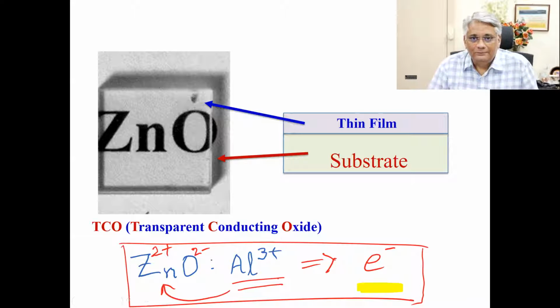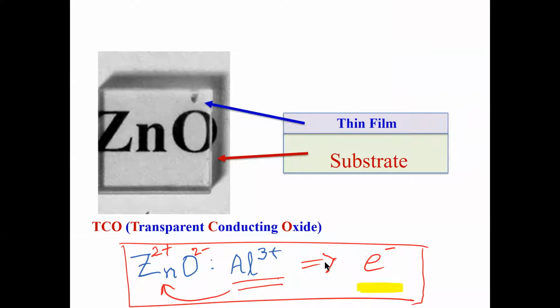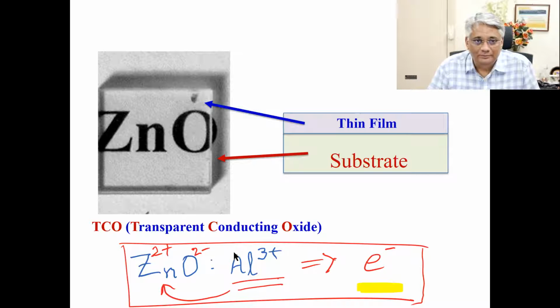Okay, that's how. So these excess electrons, I also mentioned again to reiterate the fact that the dopant levels are normally anywhere from 3 to 5%, not more than that. But that small amount of doping can cause such interesting changes in conductivity and optical properties, etc. Right? That's how the electron comes in. If you replace zinc by another divalent element, it may lead to other interesting properties. For example, a magnetic element replacing zinc, a 2+ magnetic ion replacing 2+ zinc, you may start seeing changes in the magnetic properties, but this is a classic example of how you can bring an electron into the lattice. Similarly, hole doping can also be done. All right.